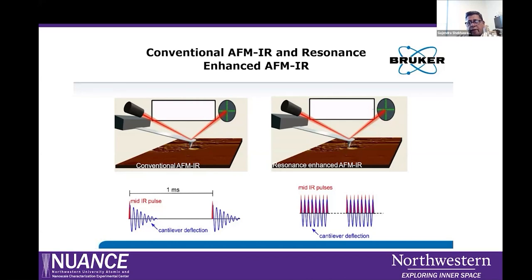But here, the signal intensity may not be that strong, so that's why we have the option of resonance enhanced AFM-IR. When there's a thermal expansion of the material, we can scan the frequency range and find the contact resonance of the cantilever. If we can excite the contact resonance of the cantilever, we can amplify the signal. So resonance enhanced AFM-IR is the best option for us because we can amplify the signal.